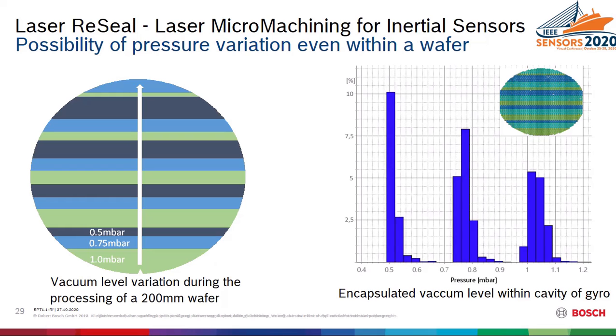Within the histogram plots on the right hand side, you can see that the included pressure differs slightly from the desired set point. As pointed out in the previous slide, we are actually measuring the Q factor of a resonator, from which we calculate the included pressure. But of course, the Q factor is also influenced by other parameters like trench inhomogeneity, but there might also be some outgassing of included residuals after the reseal process was finished. So there's room for even improving the actual pressure distribution, but please keep in mind that we were already able to improve the Q factor by roughly a factor of 3 due to the introduction of the laser reseal process, which enables many new features for the actual inertial sensor generation.